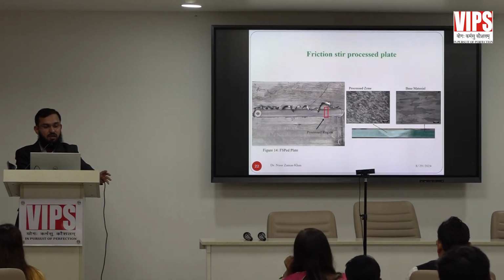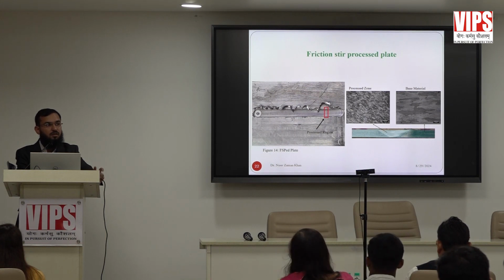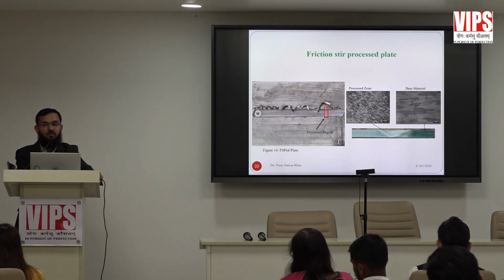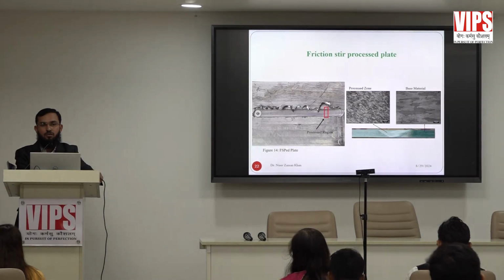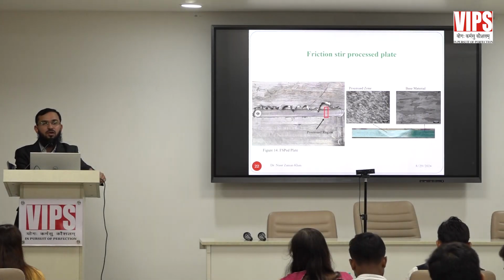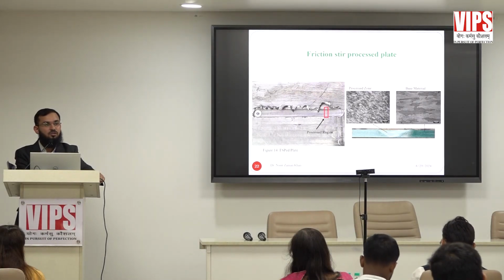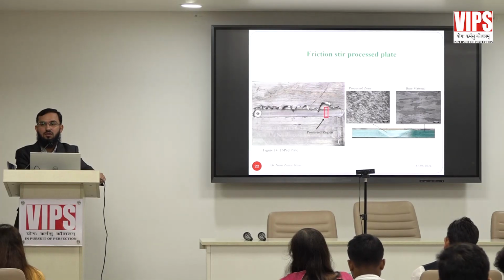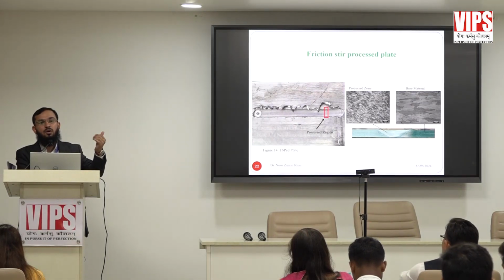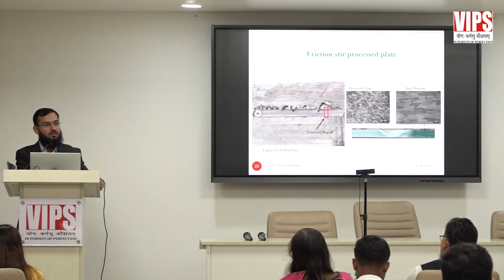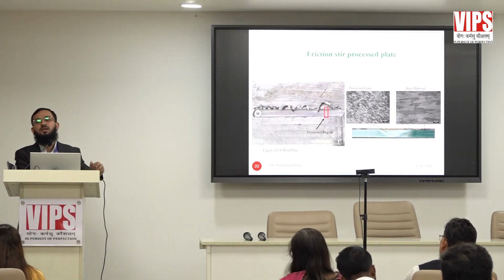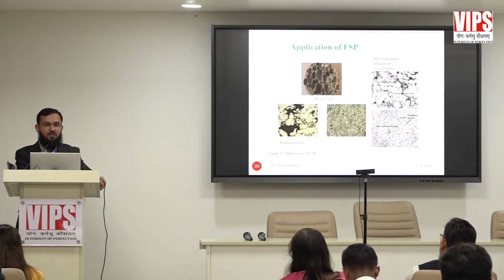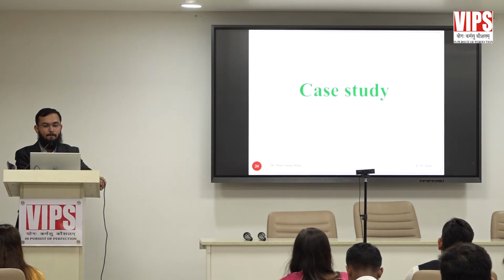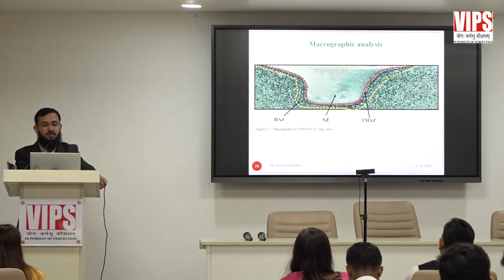Experimental setup, schematic. Just see the difference in both the figures: process zone and base material. What's the difference? If you can see, the grain size of the base material is large. And after friction stir processing, you can see the process zone grain size. It can reduce the grain size from even 80 micrometers to 0.9 micrometers. So if we reduce the grain size, we can increase the strength and the hardness. These are possible applications of friction stir processing. Case study. Okay, I'll move on.